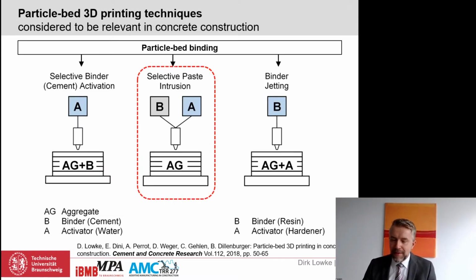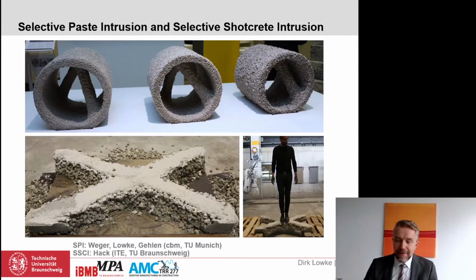Okay, let me now briefly say a few words about the selective paste intrusion method. In the selective paste intrusion method, the particle bed consists of granular sand, and the selectively applied fluid is a cement paste. Recently, together with my colleagues Norman Hack and Harald Kloft, we have scaled up this concept to particles with a diameter of more than 30 millimeters. In this case, the fluid phase was a fine-grained shotcrete.